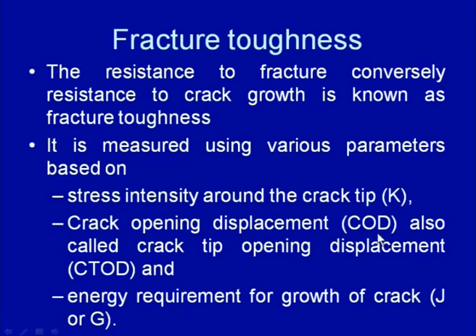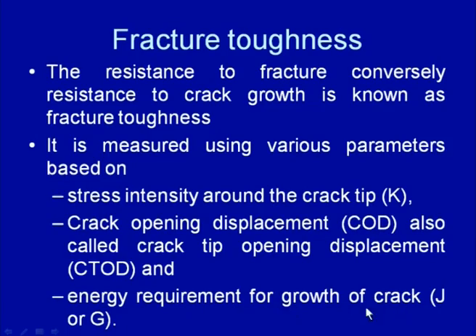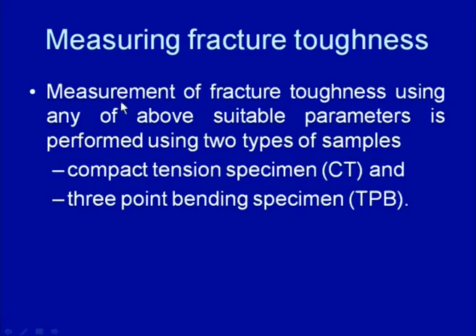Then there is the crack opening displacement, called COD or also CTOD, crack tip opening displacement, and the energy required for the growth of the crack, for which we use the J or the G parameters. We will be talking mainly about the stress intensity factor parameter, which is used for plane strain conditions, especially when the yield strength of the material is high and ductility is very limited, while the crack opening displacement and the energy related parameters are used for somewhat ductile materials.